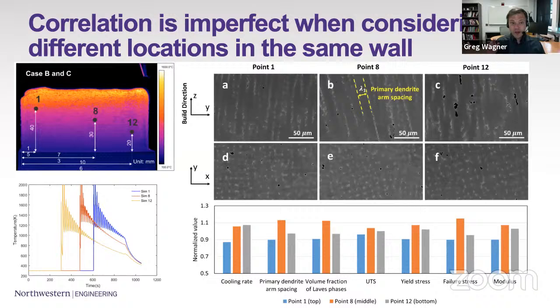So we're talking about the temperature rate of change as you pass through that solidification region for the last time. So really, it's ignoring in a way everything that goes on after that last solidification step. And you're probably already looking at these results, and you see the trend is not so clear anymore. Our cooling rates are increasing as you move down the wall. Even the dendrite spacing, which itself is a hard measurement, is not showing this trend.